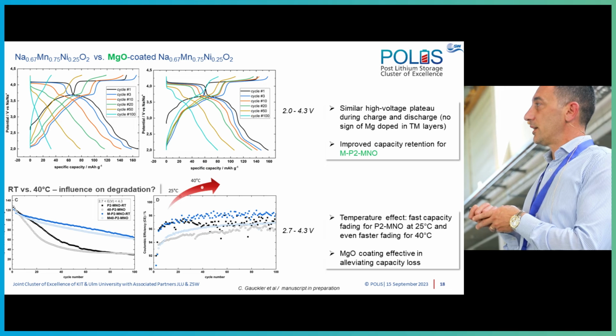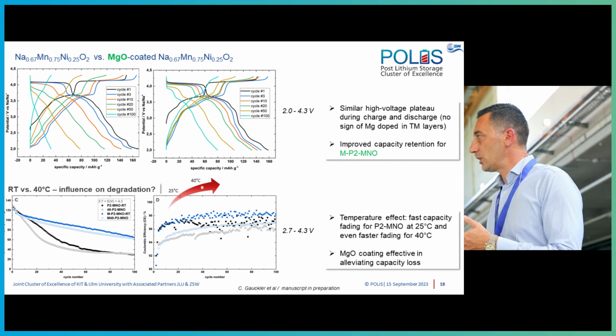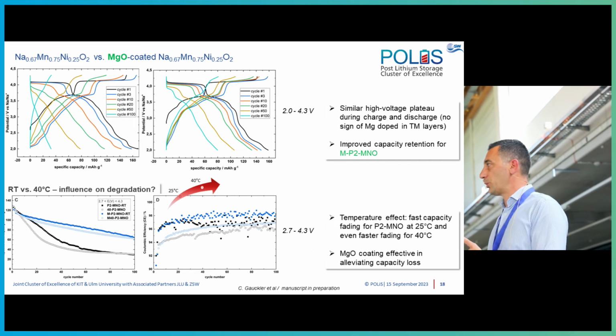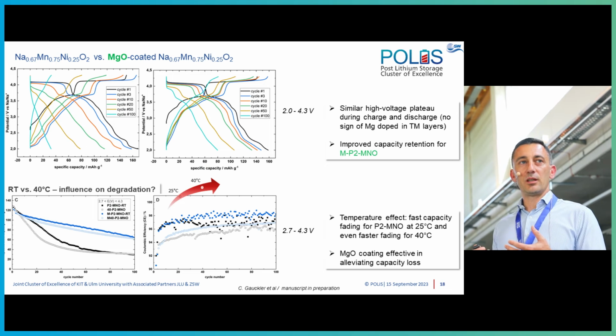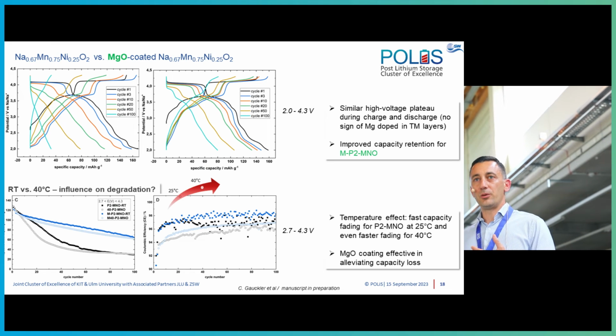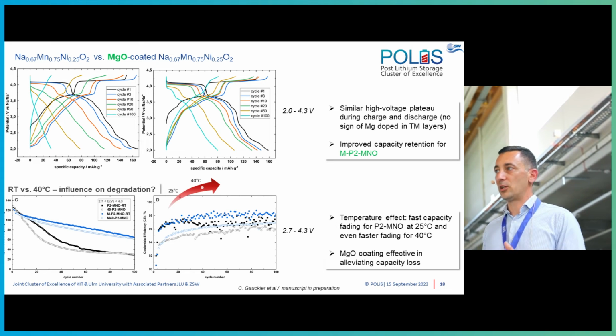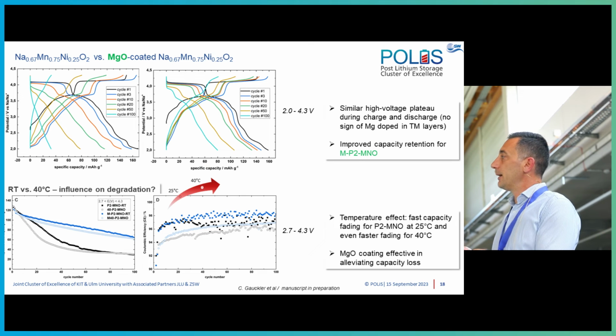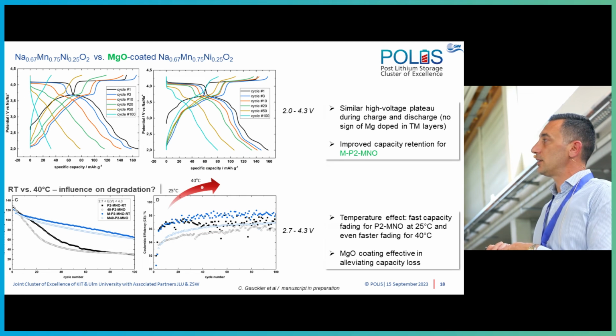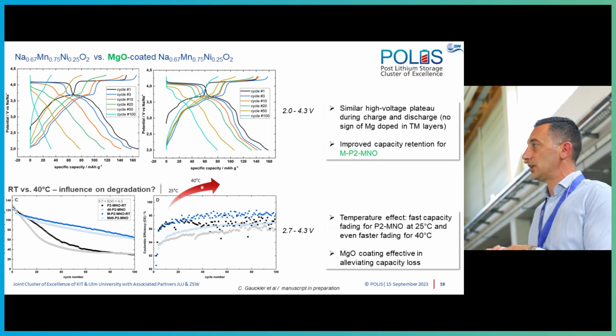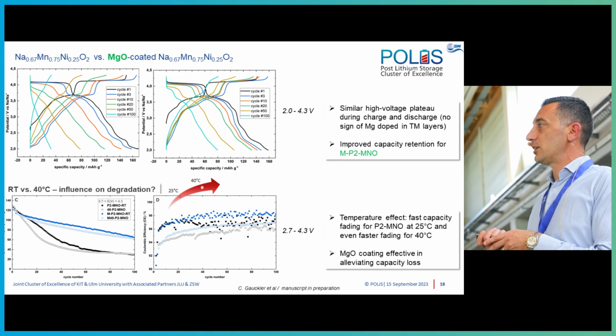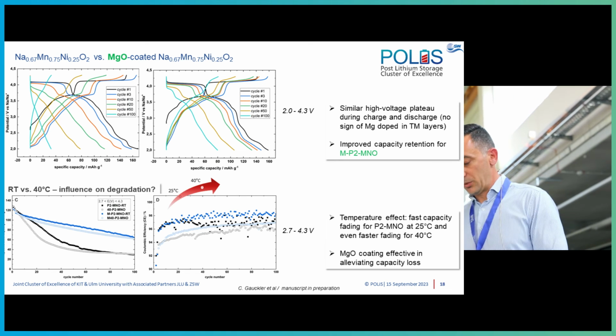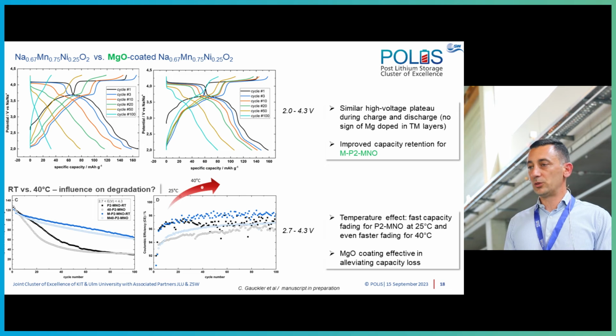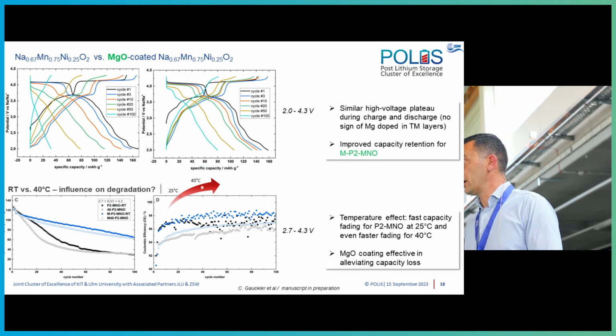Even better if we reduce the potential window to 2.7, 4.3. This would be basically the potential window that you are able to access in a full cell. And what we see is that even by switching from 25 degrees C to 40 degrees C, the capacity degradation of the magnesium oxide coated material is actually not affected.